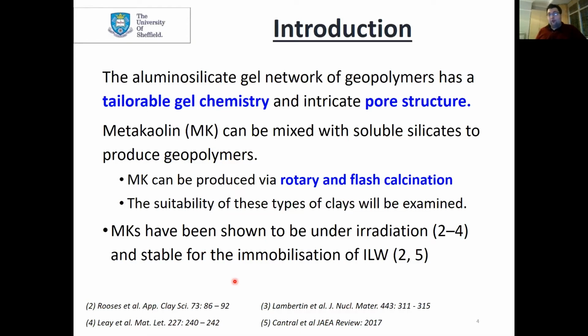So we don't want to do that. What we're trying to do is make something with a big enough pore structure to let the hydrogen gas out, but not so small that it can't get out. But if it's too big, you can leach out your radiation. So it's really about finding a nice envelope formulation.